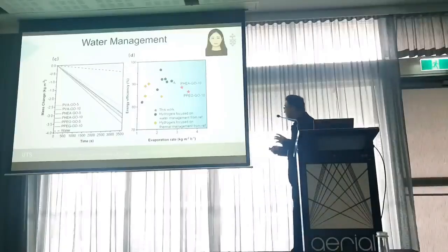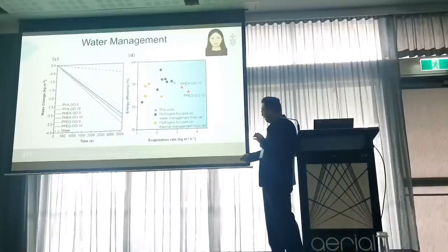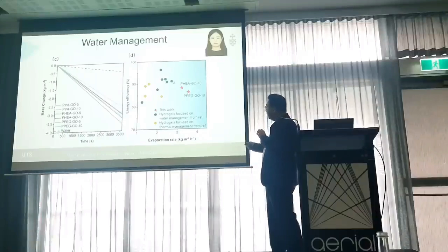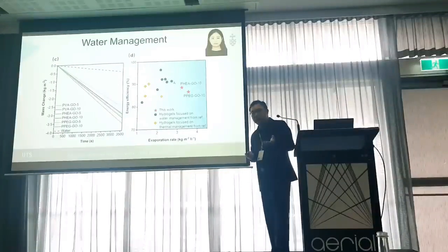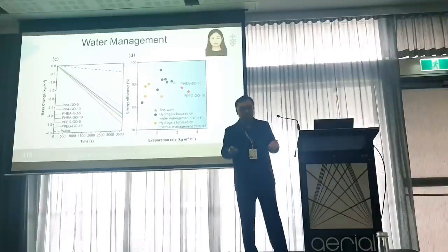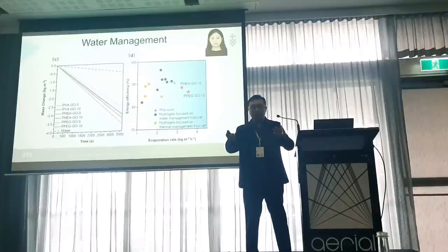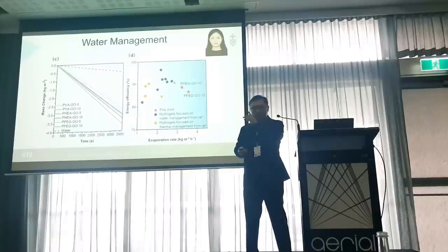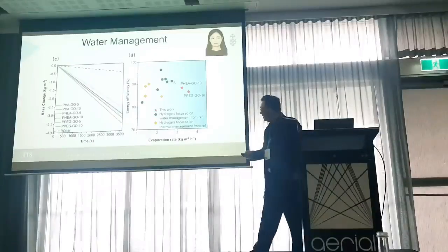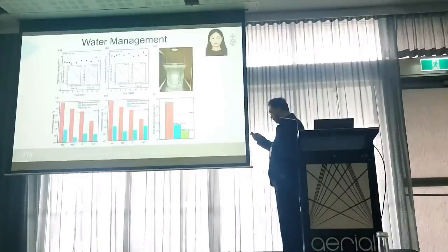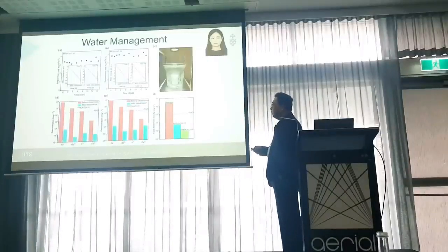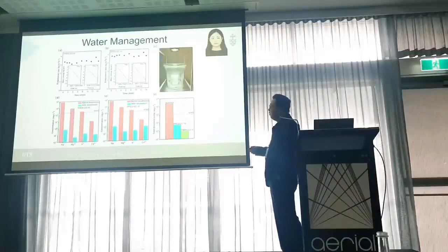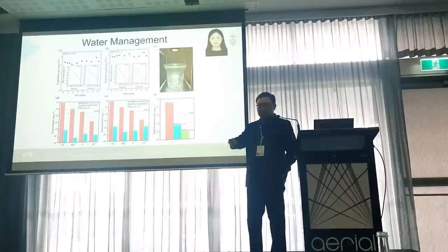And this work was conducted in 2022. At that time, we found that this 3.6 value is the highest compared to all the conventional and 2D hydrogel systems. But in the latest study we conducted this year, we broke this record. So definitely, we will test the SVG performance of this hydrogel against seawater.